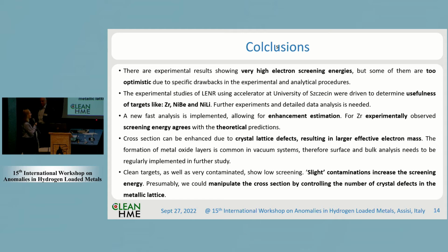Cross sections can be enhanced due to crystal lattice defects, and this results in a larger effective electron mass. So we should implement bulk and surface analysis into further studies. A clean target and a very contaminated target will show us low screening. Slight contaminations will increase the screening energy. So we think that in the future, if we know which amount of contamination is good, we can actually control the number of crystal lattice defects and then manipulate the cross section. Okay, thank you very much.